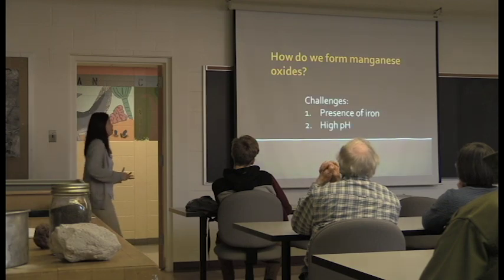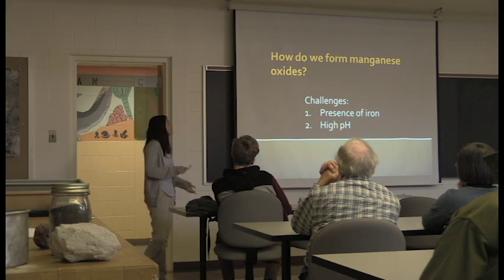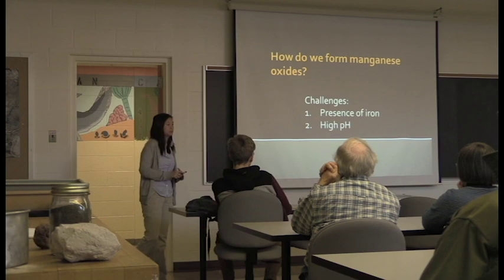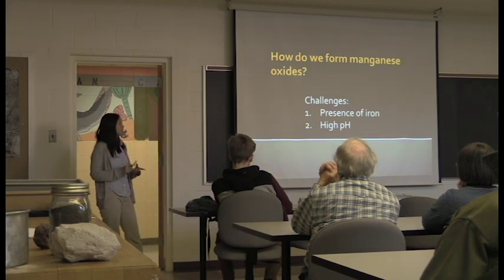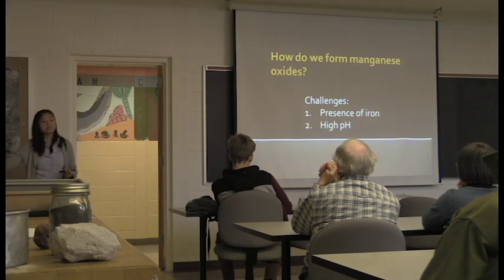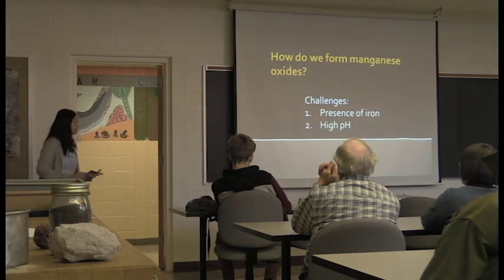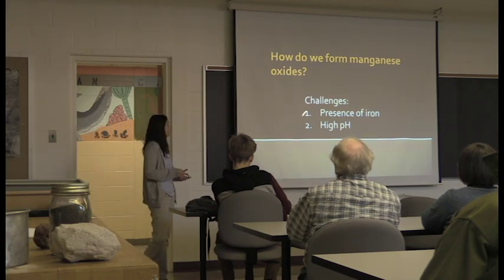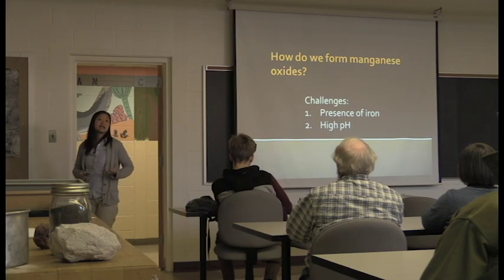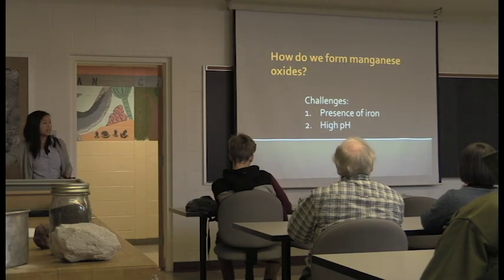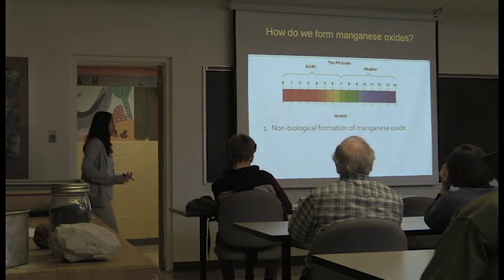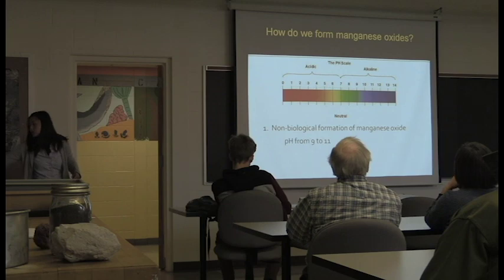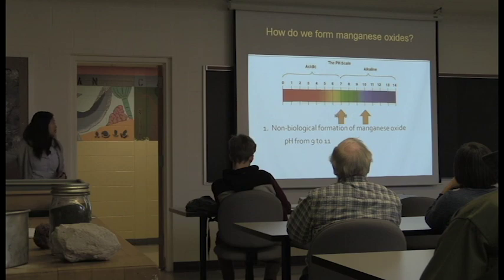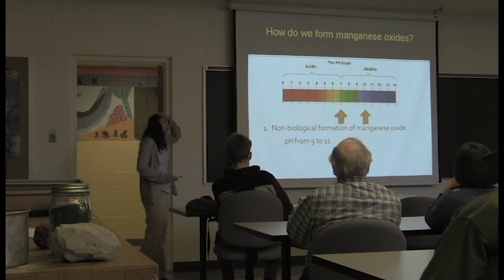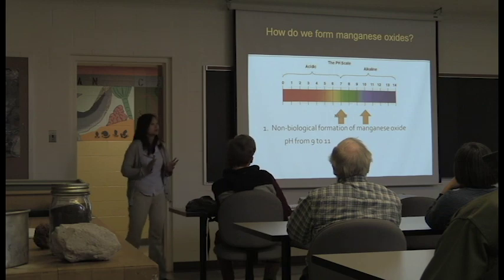The challenge about forming manganese oxides in our acid mine drainage treatment system is that the presence of iron can prevent the precipitation of manganese oxides. You also need a relatively high pH for manganese oxide precipitation to occur. One nice thing is we've already talked about how we treated for the presence of iron, by precipitating it out as iron oxides. Well, we still have this pH issue. In the non-biological formation of manganese oxides, you need a pH from 9 to 11 in order to have the manganese oxide precipitate out. Unfortunately, most of our acid mine drainage systems are treated to a pH around 6 to 8, which is a little bit more neutral.